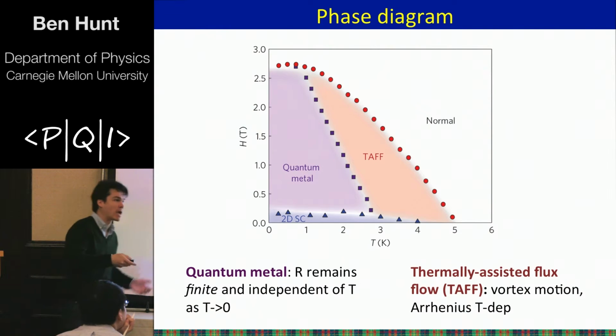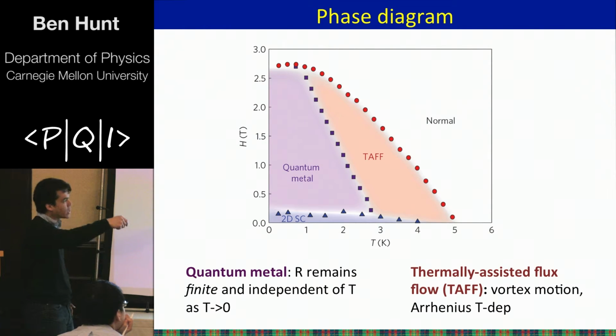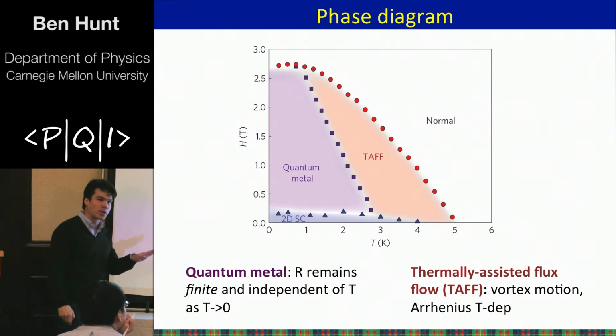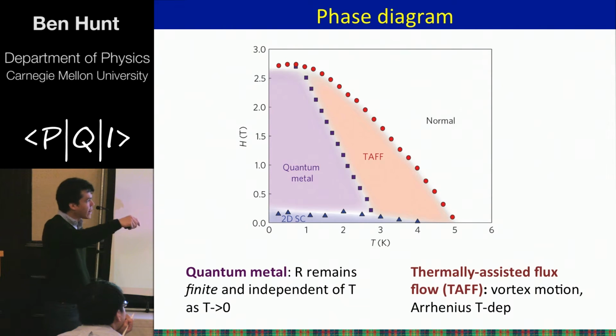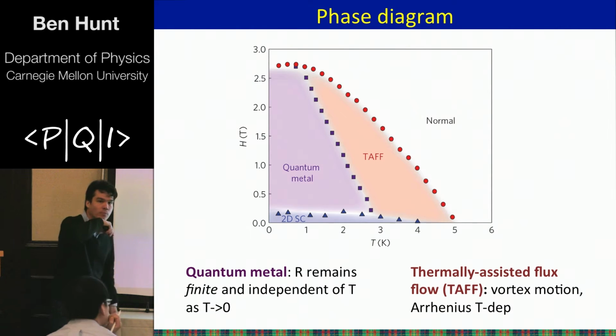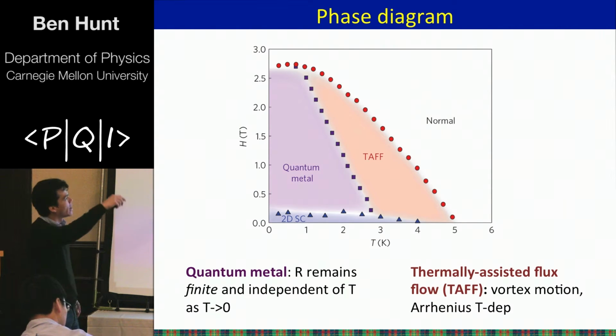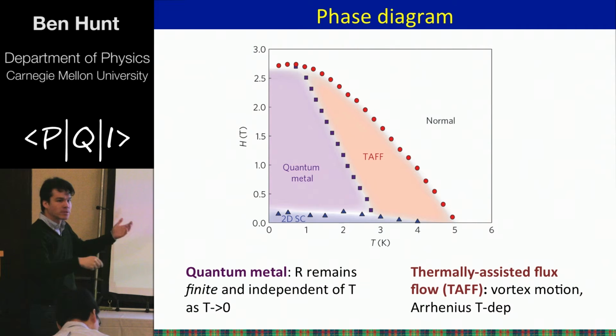That's the activated behavior. Importantly, we do observe a two-dimensional superconducting phase at finite magnetic field, but that's a very, very low field. That's only about 0.2 Tesla or so. And then for a very large, I would say relative to the old observations, for a large area of the phase diagram, we observe this